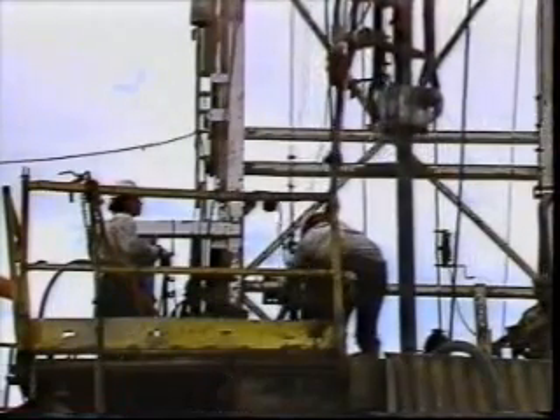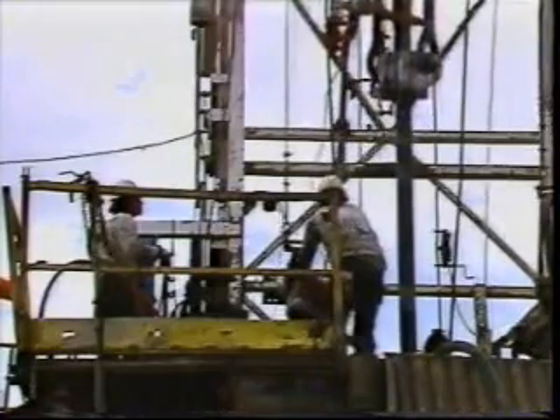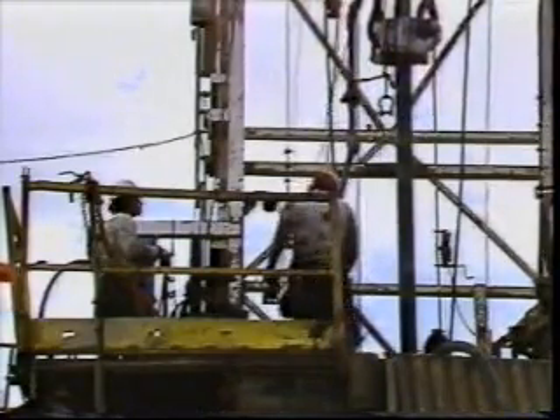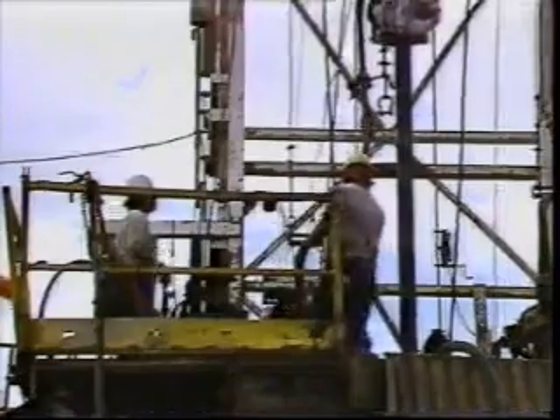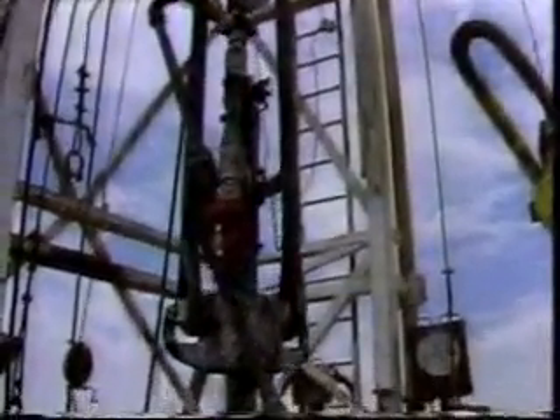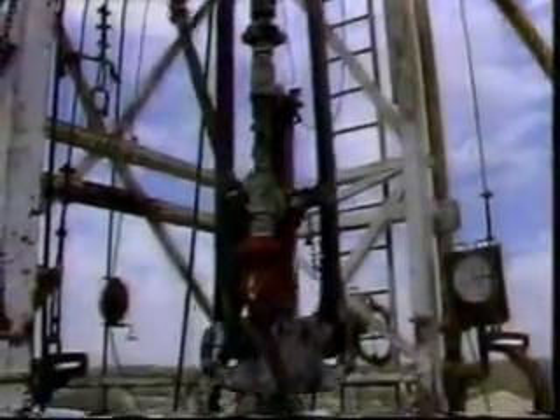The reason for pipe movement was brought about by a study within the company that showed that if you didn't do anything but run pipe to bottom and cement it worldwide, your success ratio was approximately 50%. If you moved casing and didn't do anything else, kept your slurries the same, then your success ratio increases to approximately 90%.